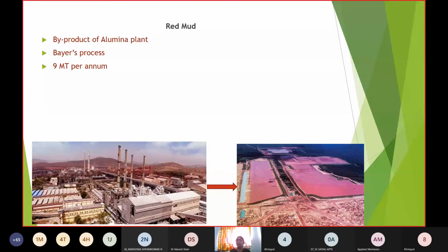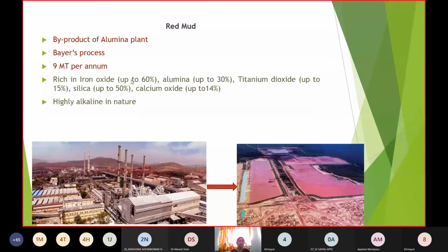So, the red mud, having its attributes of iron oxide, alumina up to 30%, titanium dioxide up to 15%, silica up to 50%, and calcium oxide up to 14%, can be used as one of the substitutes as a land reclamation material, or it is also acting as another raw material to extract the ores that are present, like titanium or iron oxide that is present inside this material. And its pH, because caustic soda is used during Bayer's process, the pH of the red mud that is coming out of this process is also very high.